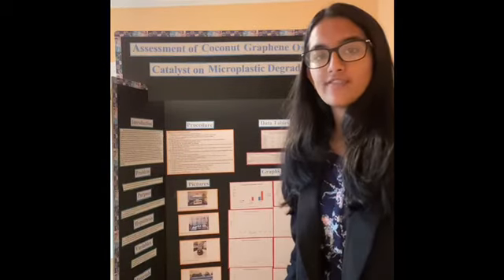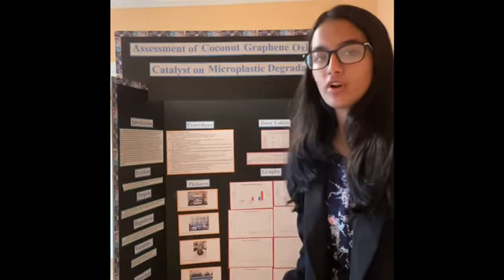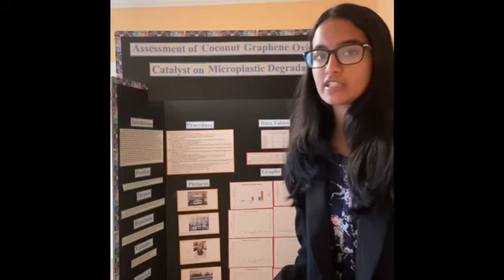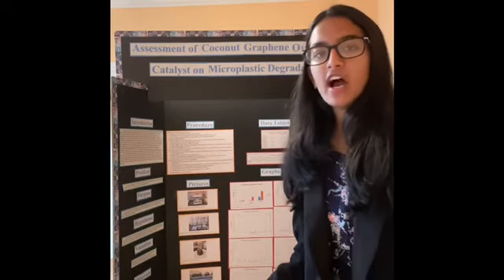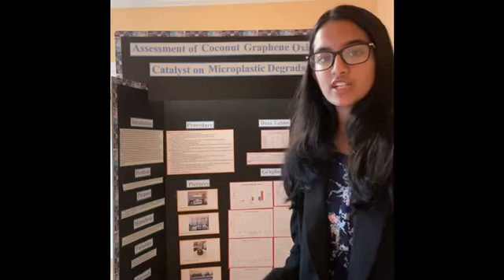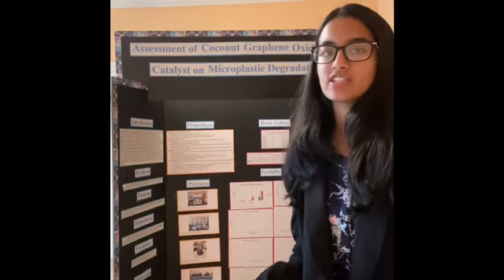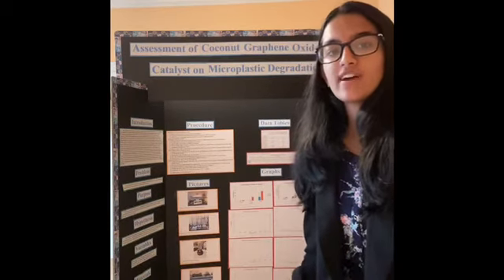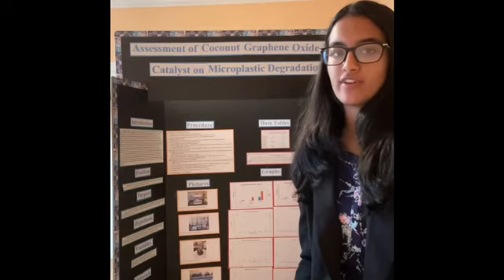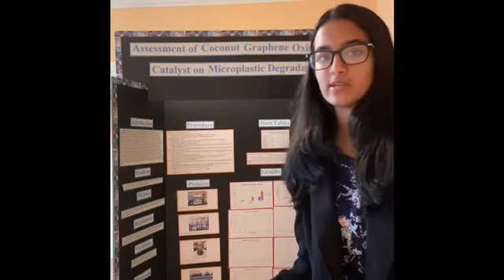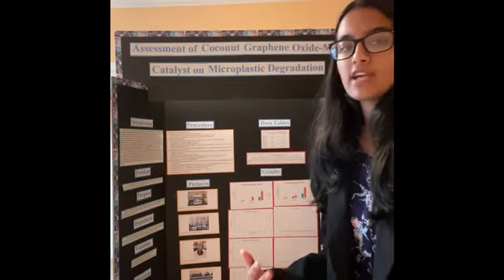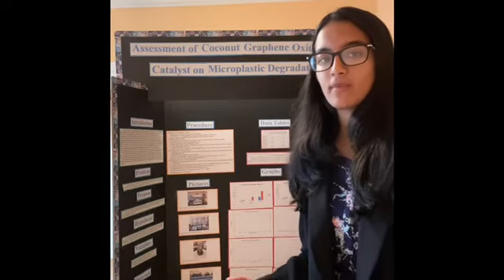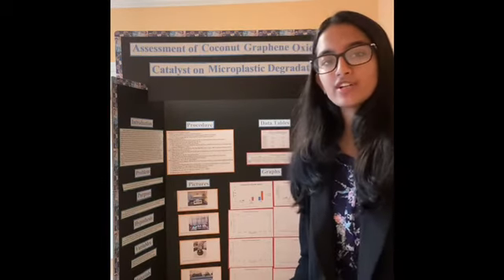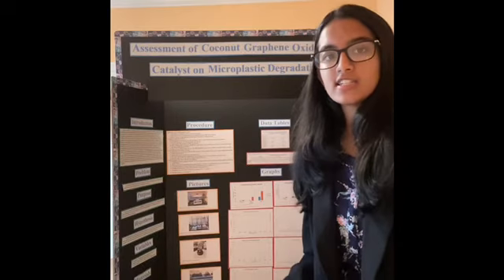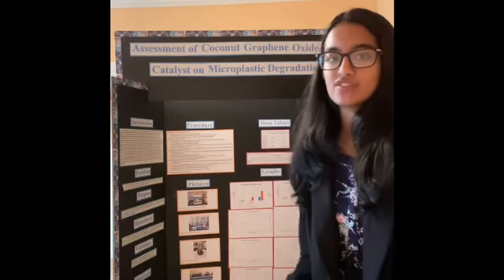In my results, I found out that the catalyst did help more effectively degrade the microplastics than the control, which contained no catalyst. I also found out that as the time increased, the catalyst more effectively degraded the microplastics, so the 5-hour catalyst sample was the one that had worked most effectively with a 16.5% mass loss. I also performed FTIR analysis and XRD on my coconut charcoal, my coconut graphene oxide, and the catalyst to confirm the composition of those substances.